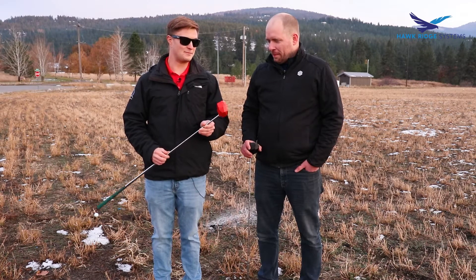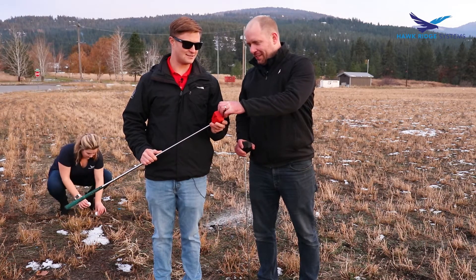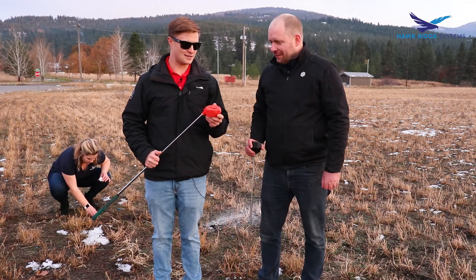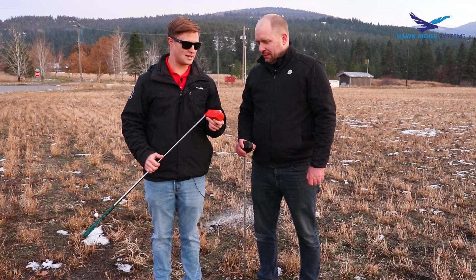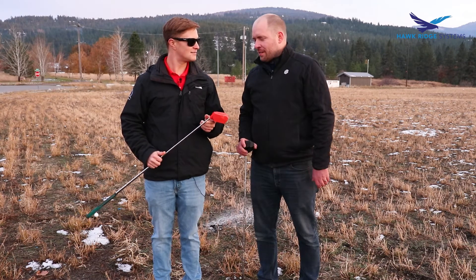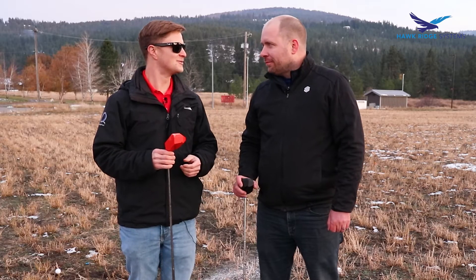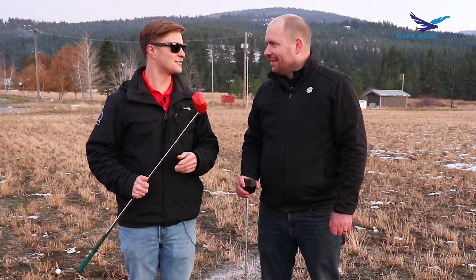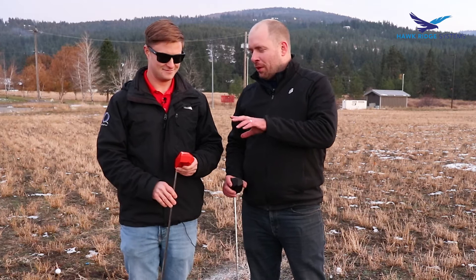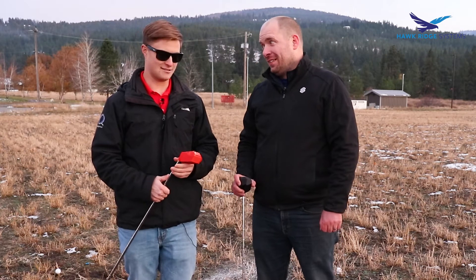So the ABS club, like I expected, not so good. Got a little delamination there. I kind of expected the whole thing to just explode, so I'm a little surprised it's still mostly together — just a little delaminated. I think that's why ABS has been one of the most common 3D printing materials; it's very tough. It was really weird to swing though because it's so light. I did like one millimeter wall thickness on that and about 30-33% infill, so it's pretty tough but very light still.